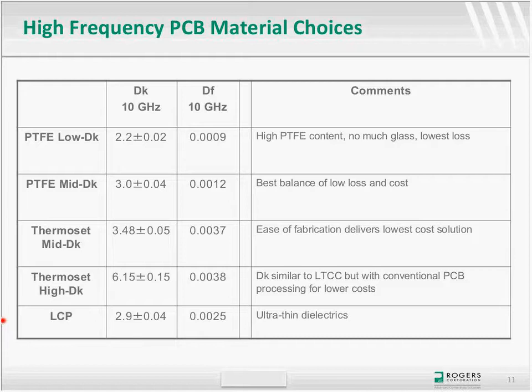So indeed, I would say it's a lot more specific application to application, what it's trying to achieve. I would say the main limitation we found in LCP has been mainly if somebody's trying to do a complex multilayer with buried vias, so sequential lamination cannot be done with the traditional LCP bond ply, so it requires using other kinds of bond plies or prepregs to be able to do sequential lamination on an LCP material.